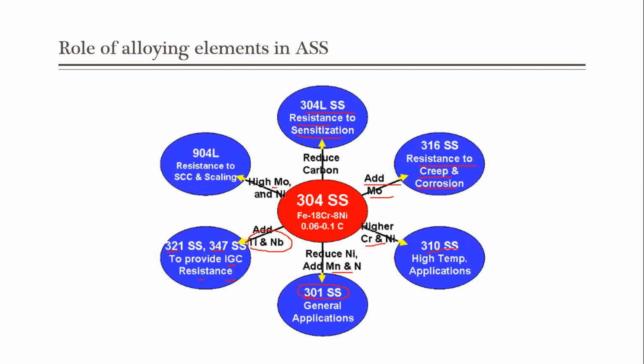And if you add molybdenum and nickel to the 304 alloy, then you can get the 904L grade, which has good resistance to stress corrosion cracking and scaling. These are some of the commonly used grades in austenitic stainless steels. If you have lower carbon, then you get 304L. If you have more of the alloying element molybdenum, then you will have 316 SS. And if you have higher chromium and nickel when compared to 304, you will have 310 SS. If you have reduced nickel and increased nitrogen, then you can get 301 SS. If you add titanium and niobium to your iron, chromium, and nickel alloy, then you get 321 SS and 347 SS. And if you have high molybdenum and nickel content, then you can get 904L SS, which has very good resistance to stress corrosion cracking and scaling.